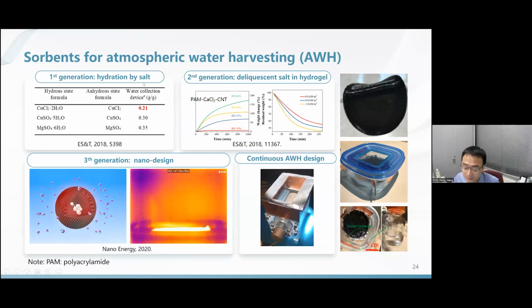We work with salts. We utilize the hydration reaction of the salt to harvest vapor from very dry air. Then we move to deliquescent salt in hydrogel. As you can see, those are real photos of our hydrogel that can harvest water from dry air. We also utilize some nano design to enhance the vapor sorption kinetics and vapor desorption kinetics. We even produce a continuous AWH design that can continuously harvest water vapor and continuously produce fresh liquid water.